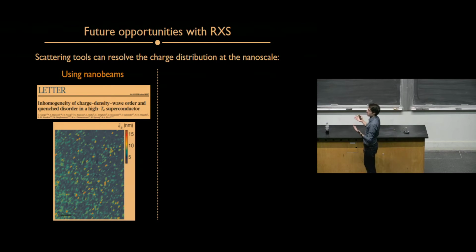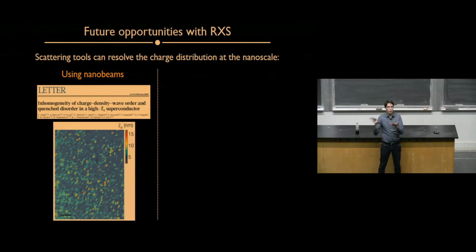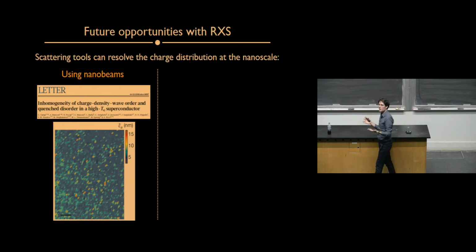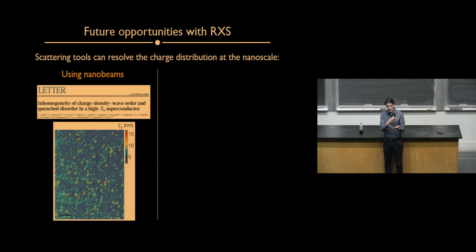So this is interesting because now we do diffraction. So we look at orders in reciprocal space. We measure how strong they are and how coherent they are in reciprocal space, but still with the ability of scanning them over nanoscopically small regions of your sample, but over mesoscopic fields of view of a few microns.